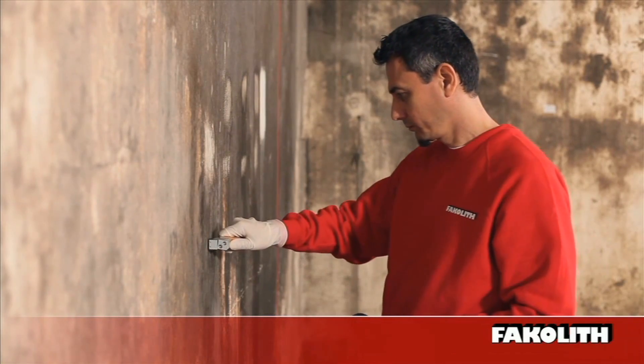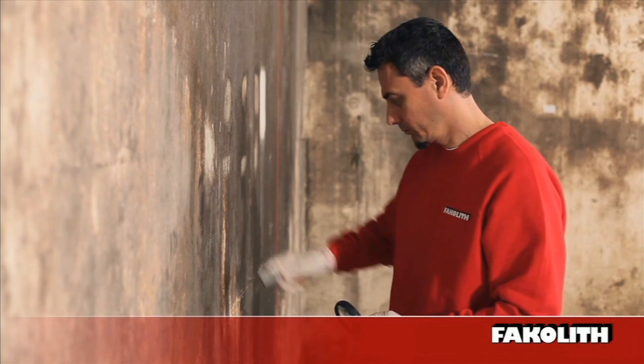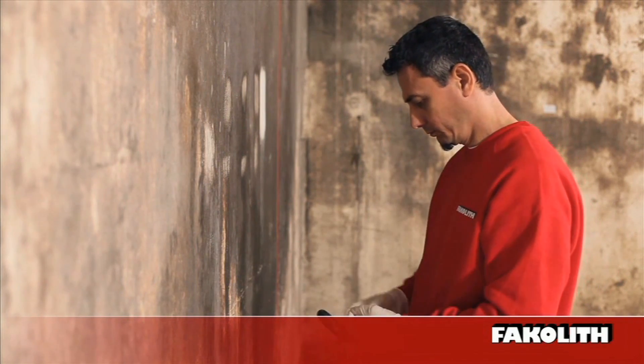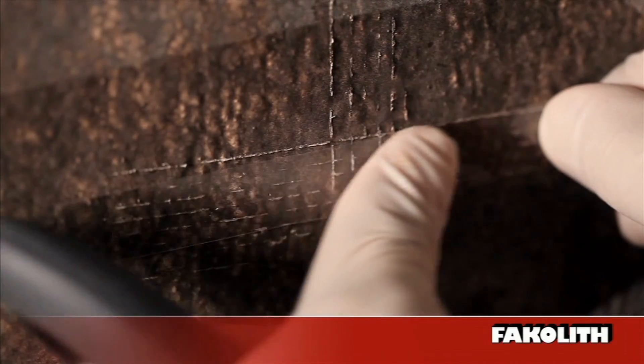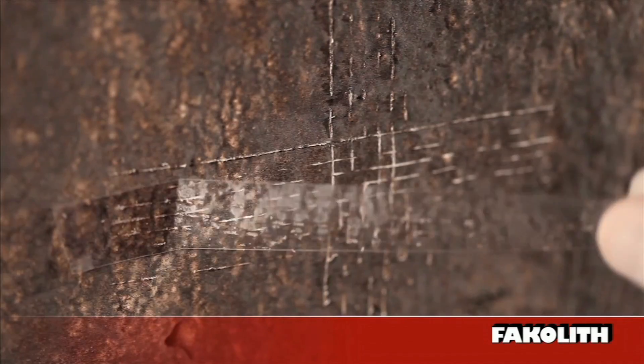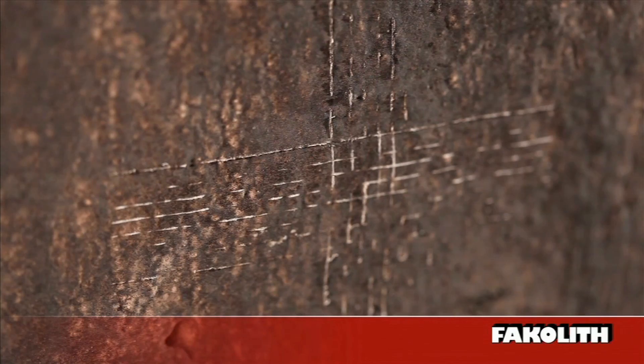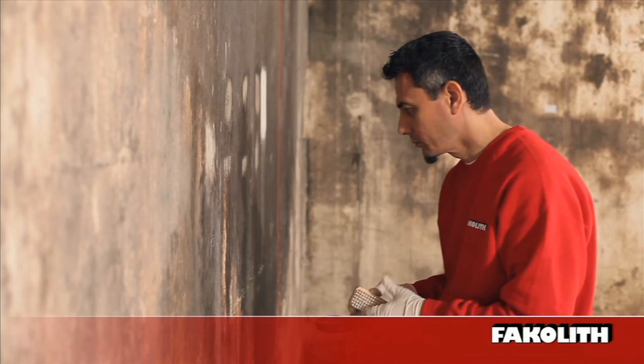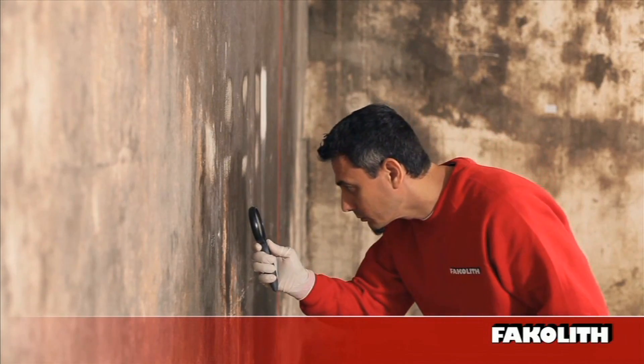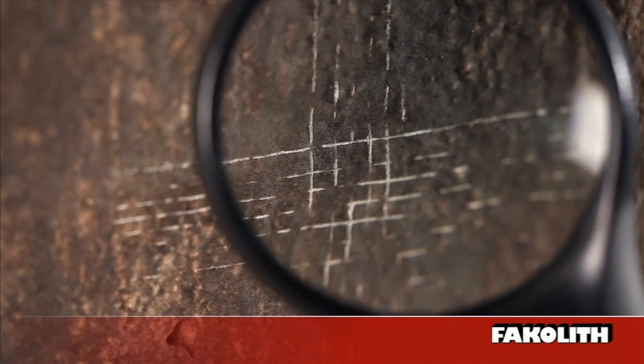We test this with a mesh cut. If the old coating is not viable, it must be removed. Coatings exposed to high humidity and regular cleaning intervals for long periods often exhibit a loss of binder. The surface becomes chalky and requires treatment to solidify.